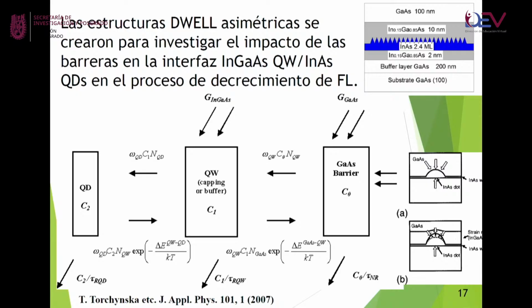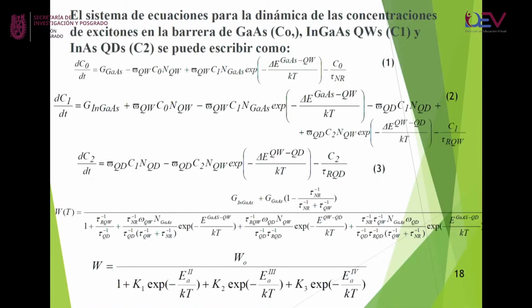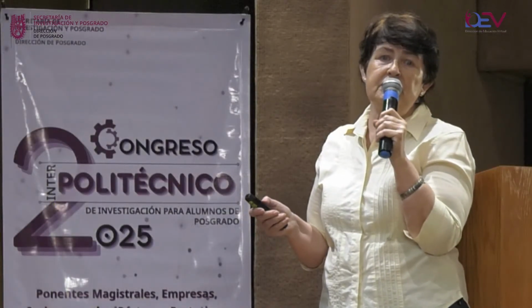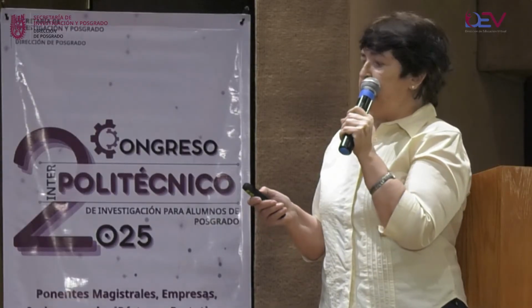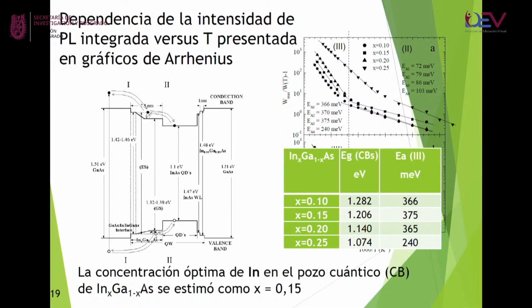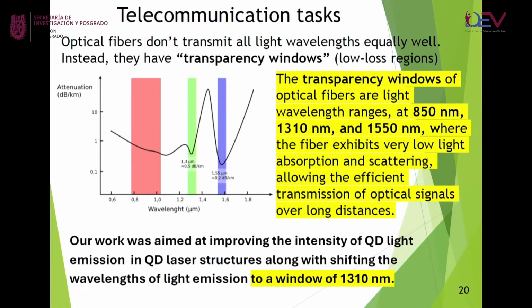You could see here part of the rate equations, which consider excitation processes and recombination processes. And these three rate equations were combined for understanding the crucial part which influenced quantum dot emission. And we show, finally, by comparing numerical results with experimental data, that the main role in decreased intensity of quantum dots is played by the confinement barrier. Due to this, we started to work with different confinement barriers.